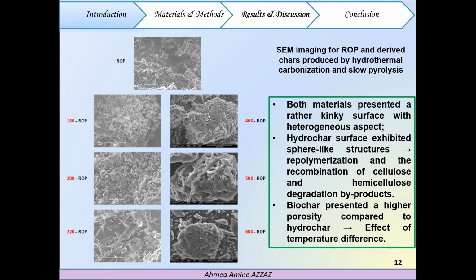So conversely, the biochars, so the pictures on the right, showed a rather porous structure with a more uniform and less rugged surface. In fact, an increase in heating intake causes a loss in mass, mainly in the form of volatile matter, which confirms the results presented in the first figure. These emissions lead to a disproportional amount of volume contraction. Accordingly, the proportion of highly disordered aromatic carbon increases inside the amorphous structure in the case of the hydrothermal carbonization. When shifting to slow pyrolysis, aromatic carbon starts to grow into conjugated, structurally arranged aromatic carbon, leading to the formation of pores, mainly in the form of slits.